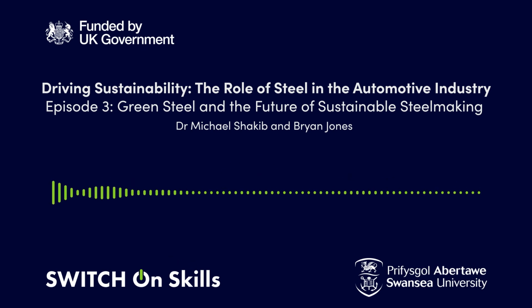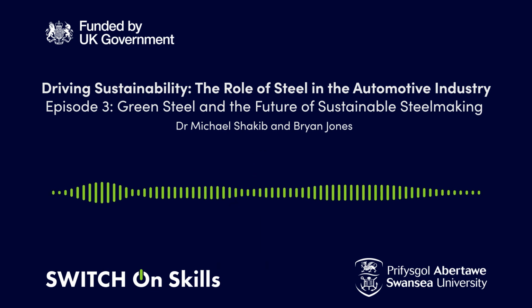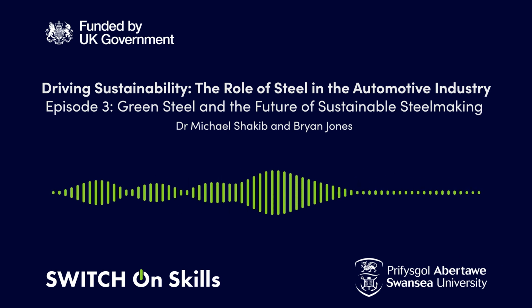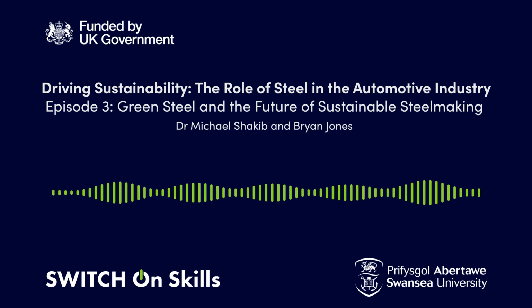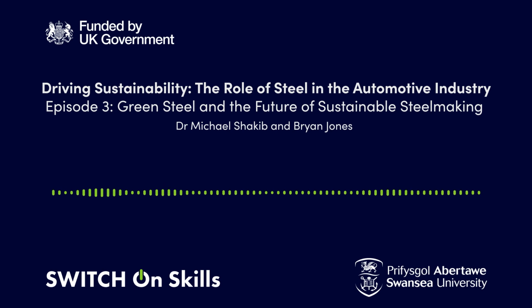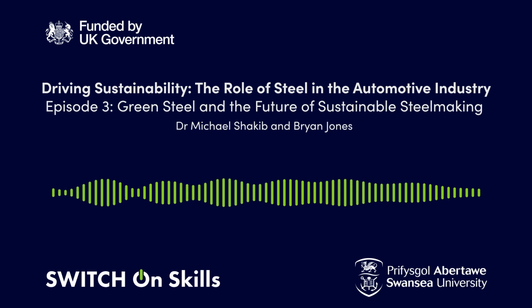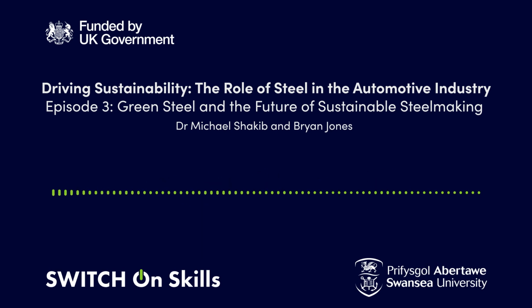So in this shaft furnace, the iron ore is progressively reduced as it descends the furnace from hematite, which is the most abundant commercial iron ore product, with a chemical composition of Fe2O3. As the lump ore and pellets descend, it's reduced in stages from hematite, Fe2O3, to magnetite, Fe3O4, and then to wustite, which is FeO. So there's a progressive change in the ratio of iron to oxygen. The ratio starts with 1.5 atoms of oxygen to 1 atom of iron, to one where it's 1 atom of iron to 1 atom of oxygen.